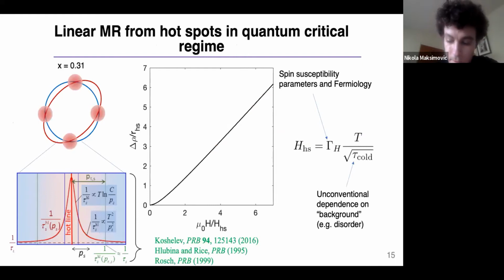In your work, were you looking primarily at the temperature-dependent resistivity? The thing about the magnetoresistance is that it's true you will get contributions from each band individually, but the regions that dominate the magnetoresistance are actually these quasi-particle sinks. So in our work, we've completely neglected the magnetoresistance arising from these cold regions.